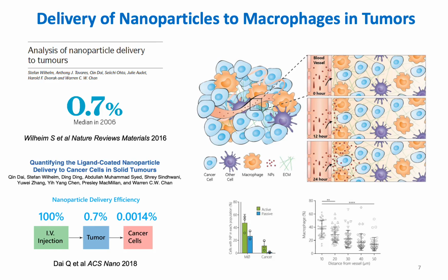Later, in 2016, Wilhelm et al. from Toronto published this controversial meta-analysis showing that most of the nanomedicines which have been developed till now for the treatment of cancer are only able to increase the amount of drug reaching the tumor in a small percentage of 0.7%. In a subsequent study in 2018, they demonstrated that functionalization of nanoparticles with ligands to reach tumor cells is not able to improve this 0.7%, and a very small percentage of drugs reach the cancer cells.